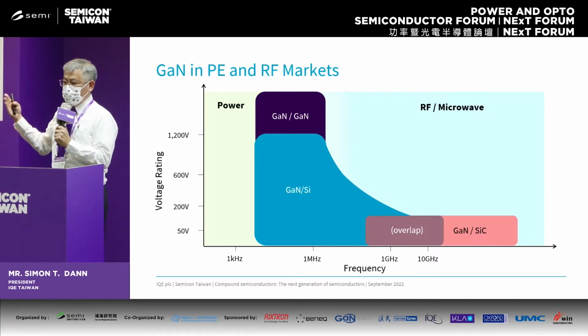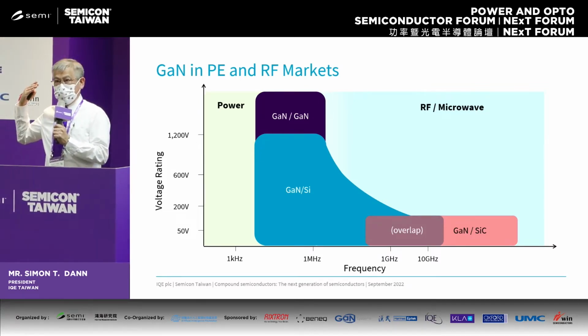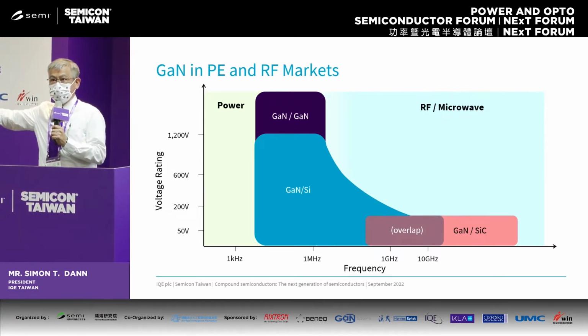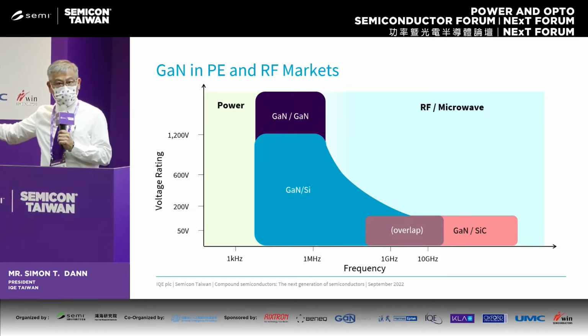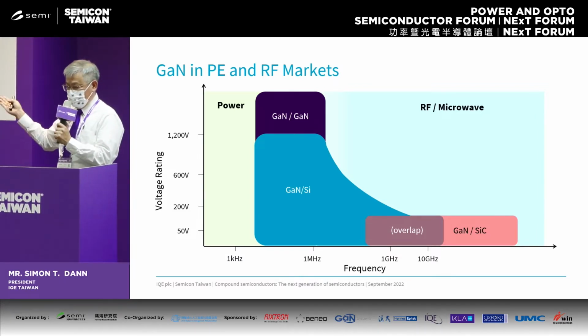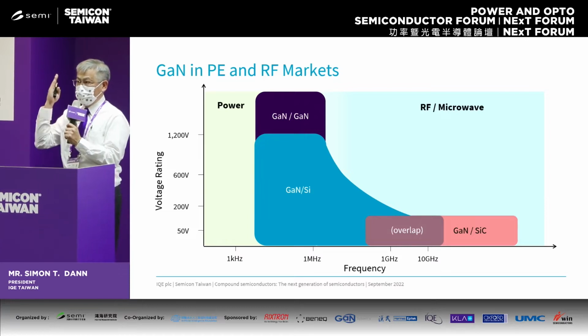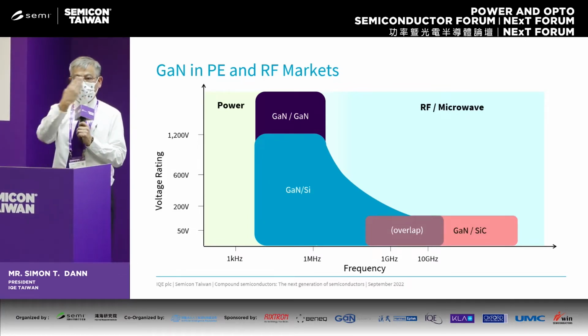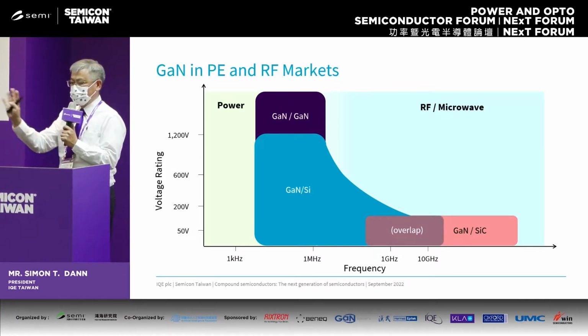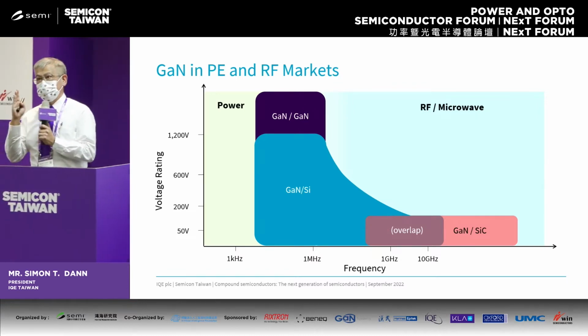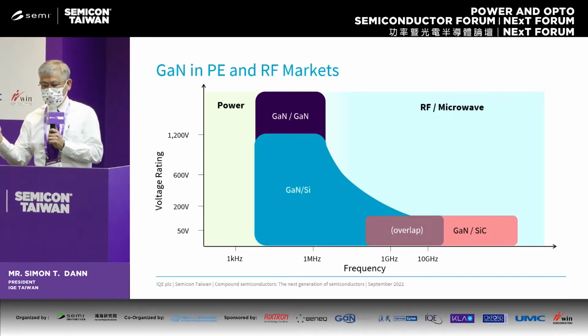For example, gallium nitride using the higher frequency, the selection of the substrate will be gallium nitride on silicon carbide, because the operation frequency is higher, the demand also the power output. So there's a selection in the gallium nitride on silicon carbide. And for the power conversion, you want the best power conversion that you gallium nitride on gallium nitride. So there's an overlap in the gigahertz range to 10 gigahertz range.